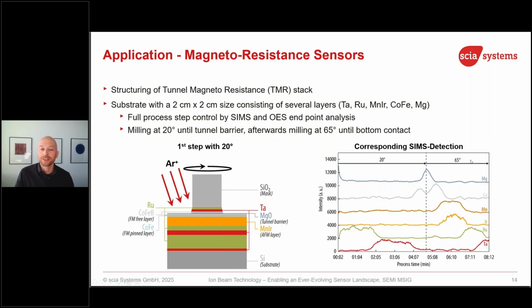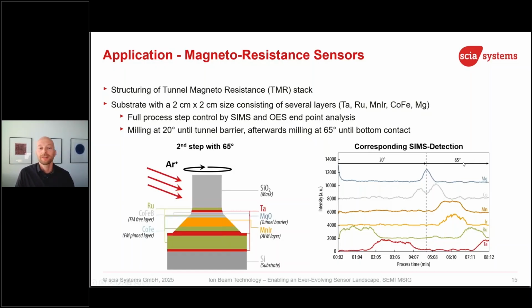And in that case, we'll tilt our substrate stage to 65 degrees and continue etching. Why is that? Because we do physical sputtering, and the material sputtered away in that lower area will finally go to the sputter shields of our chamber, but also to the sidewall here. And if we sputter metal here and get a coating on our oxide layer on the sidewall, there's a shortcut. So we would not be able to get any measurement signal anymore. So we have to make sure that the sidewall stays clean.